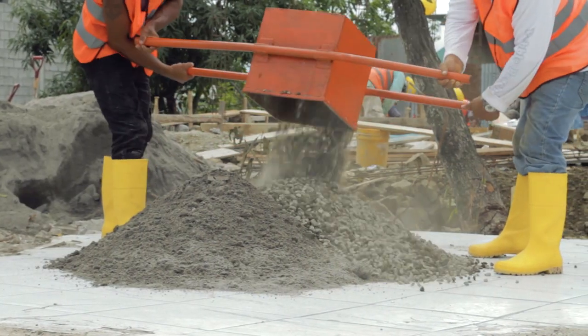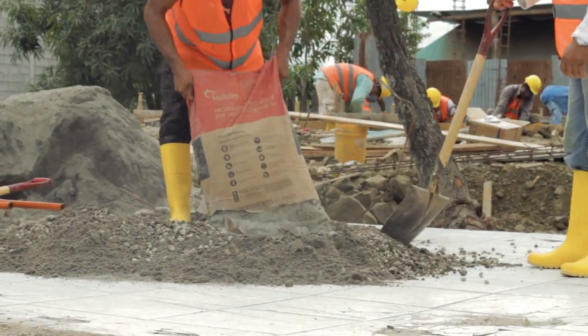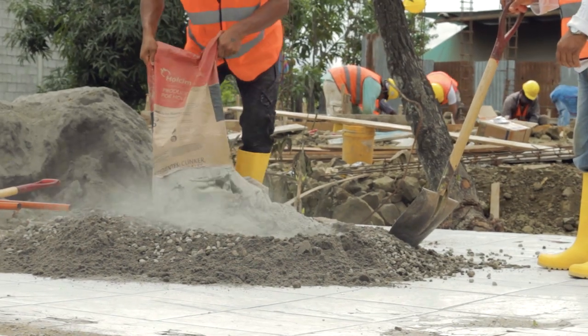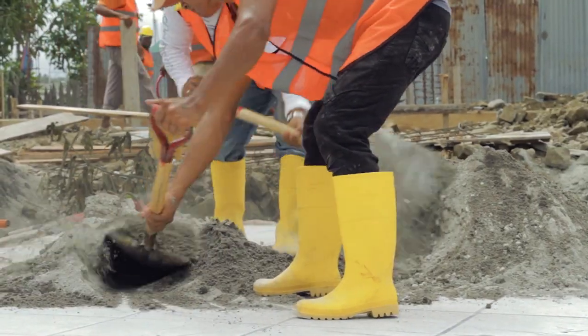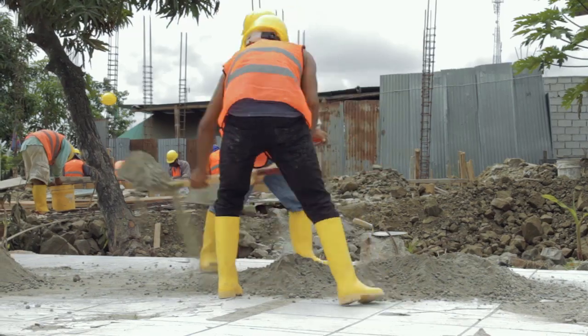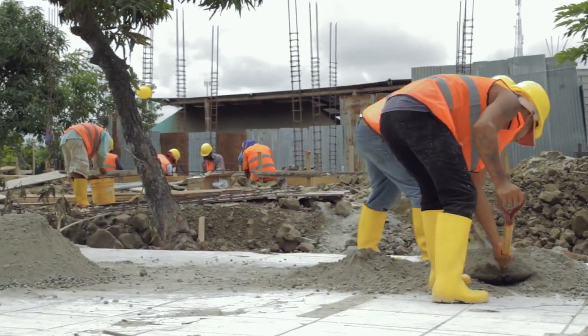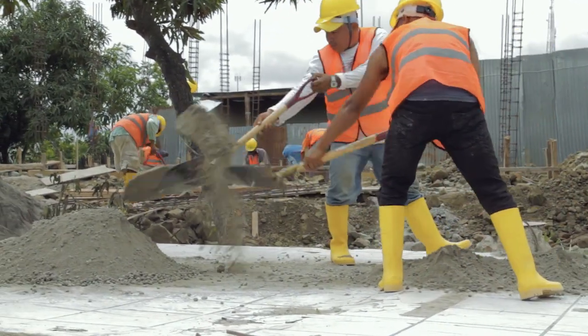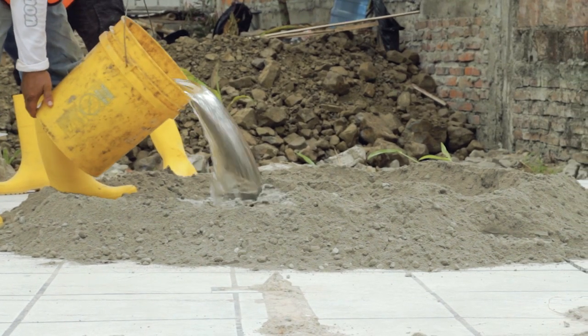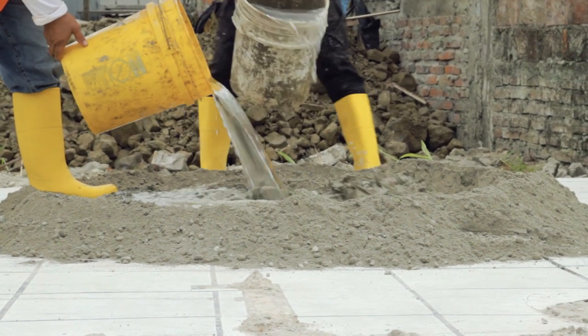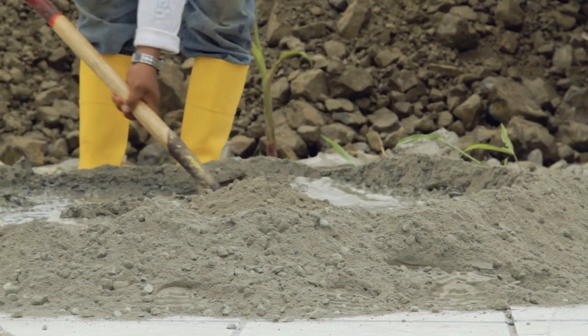1. Make a pile with the gravel, the sand and the cement, but without water. 2. Mix the dry pile by shoveling it to a new pile and repeat this by shoveling it back to the first pile, ensuring good mixing. 3. Once the dry mixing is done, add the water and mix it again.